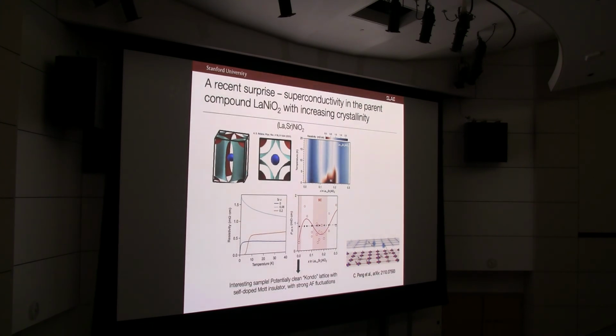So this is the phase diagram in lanthanum strontium nickelate. And if I go back to the scale of the residual resistivity in the normal state, we've now dipped down below this kind of resistance scale that I described to you earlier, such that the resistivity of this one is asymptoting to 0. We don't often get all the way to 0, but let's say 90% there by 100 millikelvin or so. We think this is rather interesting and certainly worth more materials and measurement investigation.